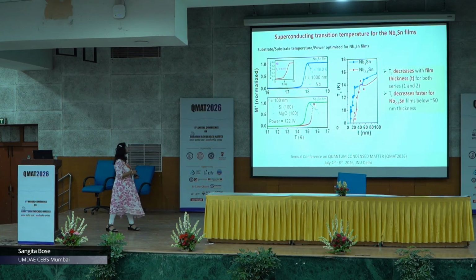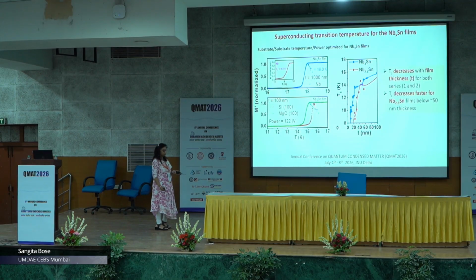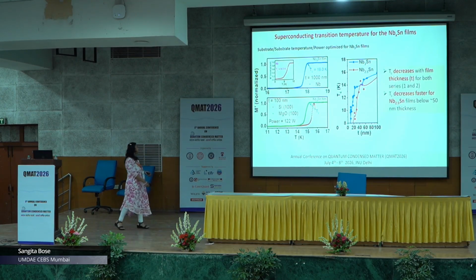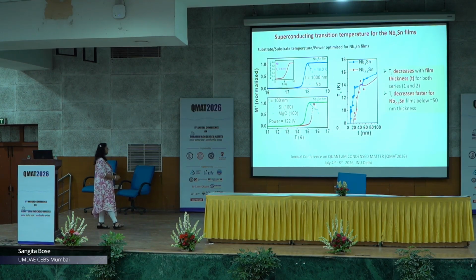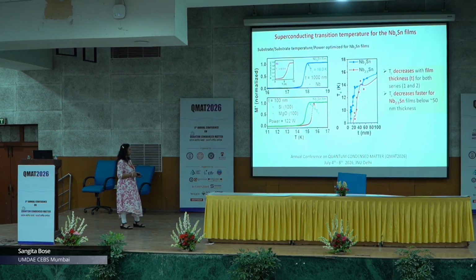So, first we satisfied ourselves that when you grow niobium tin on substrates which are niobium also, which is important for the radio frequency, superconducting radio frequency resonators which are used for accelerators. So, you see that we get 18 Kelvin Tc. Now, the main result is over here.